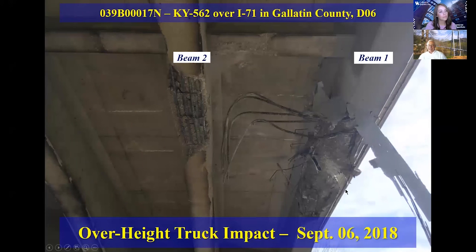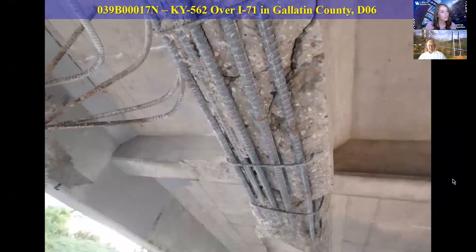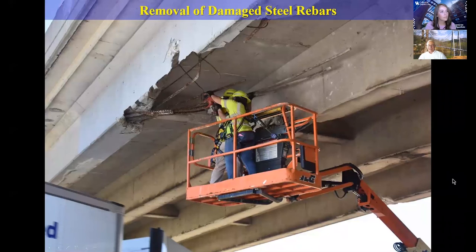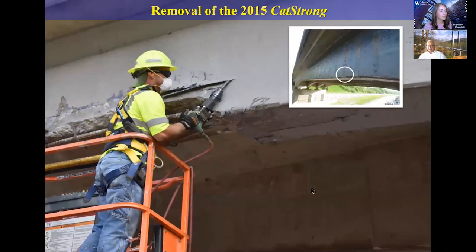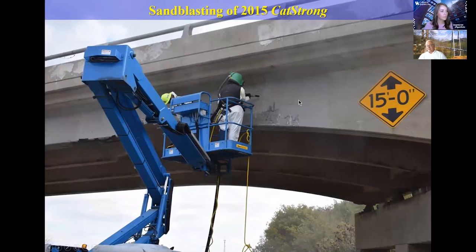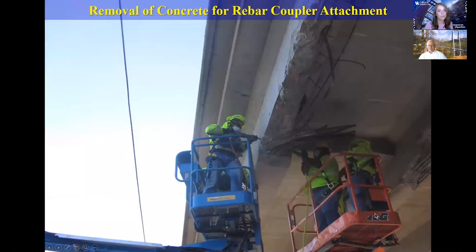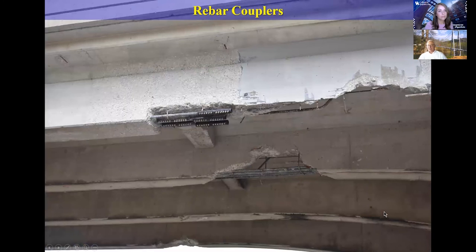But after looking at it, I figured out that yes, we can repair it. So I had to convince them that yes, we can repair it. So we came back with a repair plan. We just cut off all the rebars. It was very hard to remove the original fabric that we placed, which is a very good sign. We had to sandblast it. We could not chip it off, actually. So we cut off all the rebars and put connectors and connected all but one of the rebars.